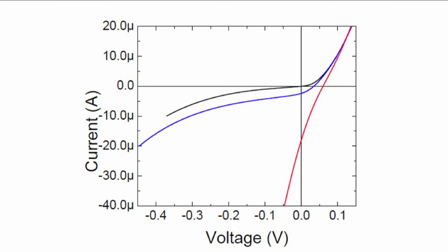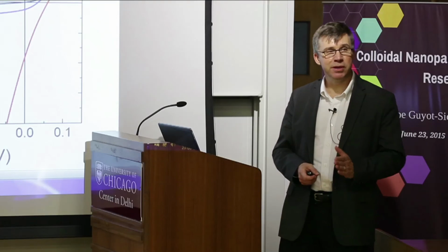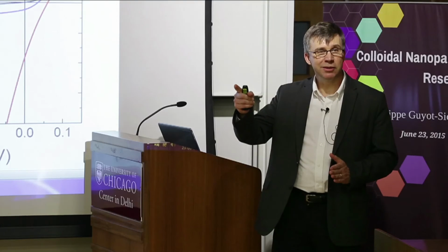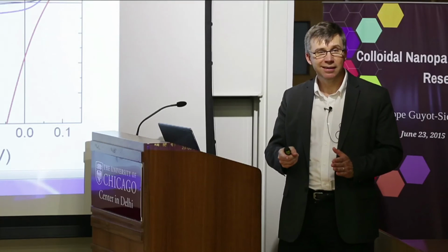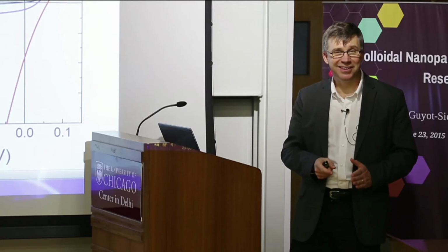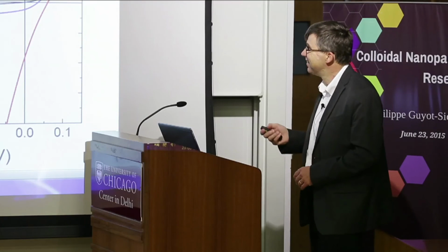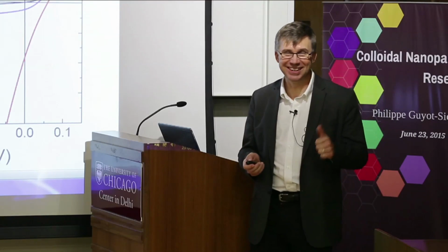And the noise, in this case, is limited by the shot noise of the current at this level, and that's a background limited condition. Now this detector is sensitive enough that if you put your hand in front of the window of the cryostat that houses it, then it can definitely see the increase of current just because the hand is slightly warmer than the background. I'm not sure that would be true if we were to put it outside on the street, because I think the background is hotter than the hand in Delhi right now. But in Chicago, it works really well.